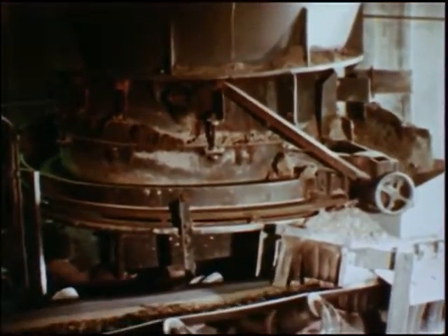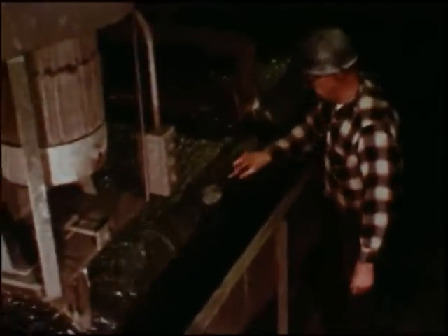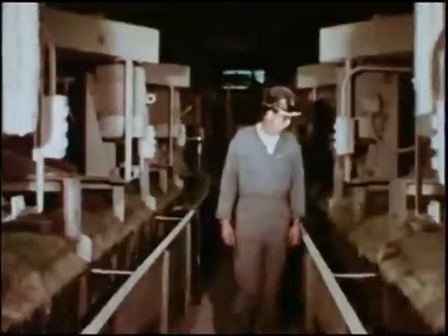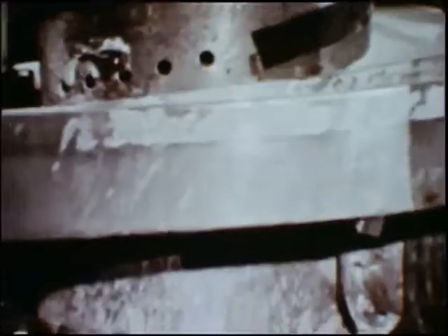The rocks are carried through further grinding and screening processes, through massive cones into rod and ball mills to pulverize the rock still more completely. After this fine ore is crushed, it is sent on to be processed further so that pure minerals may be segregated. The ore, now a pulp with water added, is subjected to flotation to separate the sulphide and tungsten minerals from the bulk ore. The scheelite particles float to the top while the waste particles drop to the bottom of the vats. Seemingly endless processes — digestion, heating, chemical treating, filtering — purify and extract the tungsten in the form of a white, sugary substance.